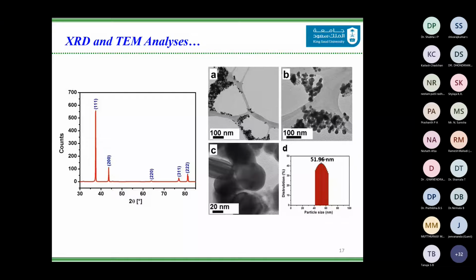The other thing that you should observe is in the TEM images, where the scale is around 100 nanometers in A and B, and you can see that the particles appear to be very, very minute. The average particle size that we got was in the range of 40 to 60 nanometers, as per the TEM image, and we found that there is a slight amount of agglomeration that is visible. However, those images are not included here, but when we took images of the nanoparticles prepared with a slightly higher amount of plant extract, the agglomeration was avoided.